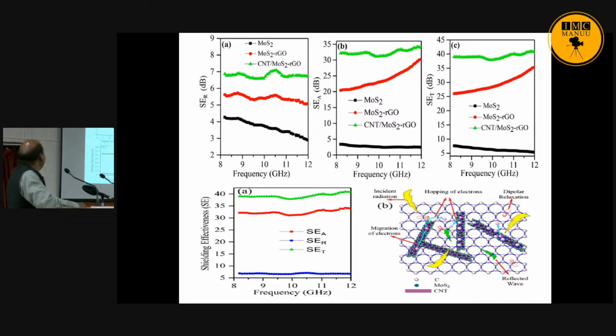If you see, this is the EMI shielding due to reflection. For MoS2 this is only around 3 or 4. If you go for MoS2 RGO, it increases to around 5. But if you take the total EMI shielding due to reflection and absorption, this is around 40. So this is a good result if you see here.